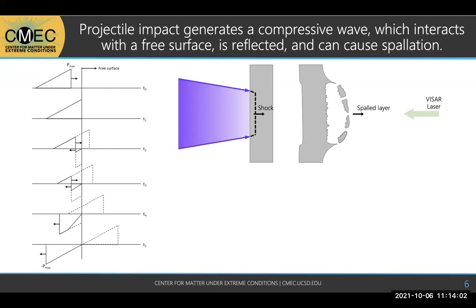So projectile or laser impact essentially generates a compressive wave that ends up interacting with a free surface, causes reflection, and then causes spallation. So I'm going to break this down a little bit more. The schematic on the left shows the movement of a pressure wave. If you think of a metal sample on the left side and then a vacuum on the right, that's what a free surface is. It's not a junction of two materials, it's a material and a vacuum. And so as that pressure front moves through and hits that back surface, the shock impedance between a metal and a vacuum is so different that you actually get a complete reflection of that wave back into the material.